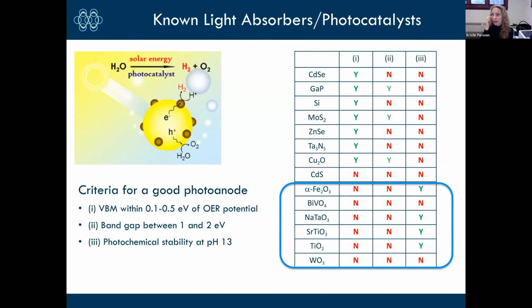In this case, we're going for alkaline because it's slightly easier than acid to find materials that are stable under high pH, because of course we're going to have to operate in water if we're doing water splitting. So this is a really important criterion, just as it was for our alkaline batteries. If you're going to operate within a media that is corrosive, you really need to screen for that property as well.